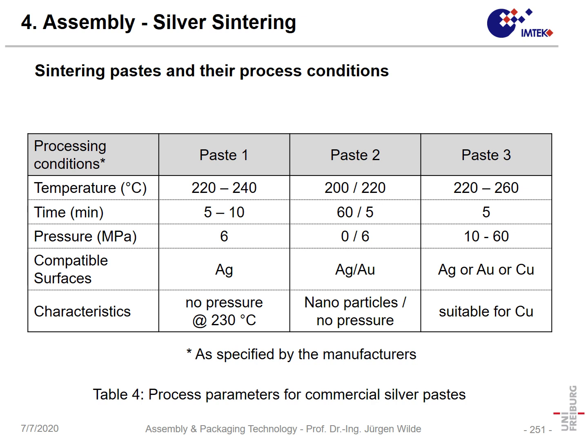Going back to the properties, for instance, one paste operates above 220 to 240 degrees centigrade. Time is between 5 and 10 minutes. That paste has a low pressure of 6 megapascal. It is a so-called no pressure paste. On the other hand, that is a so-called high pressure paste.